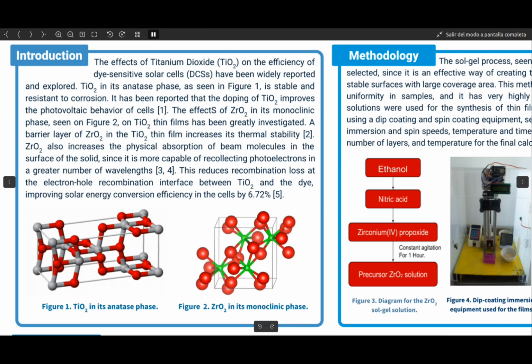Titanium dioxide is an extensively researched nanomaterial with photovoltaic and photocatalytic applications. It is attractive because of its abundance as well as its high chemical stability and resistance to corrosion. Titanium dioxide in its anatase phase, seen in figure 1, is used as a semiconductor due to its long-term stability and good photovoltaic and photocatalytic activity. For the effective photoexcitation of the titanium dioxide in the anatase phase, illumination needs to be higher than the bandgap energy of around 3.2 electron volts. It has an absorption threshold of around 380 nanometers, where around 5% of the ultraviolet fraction of solar radiation is